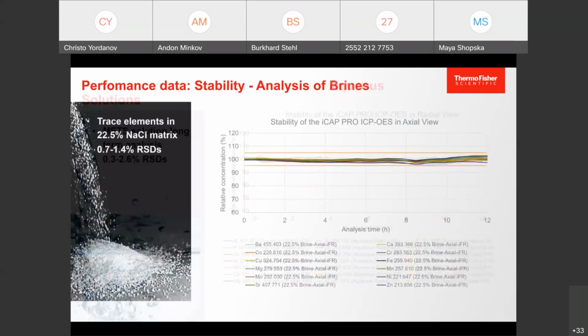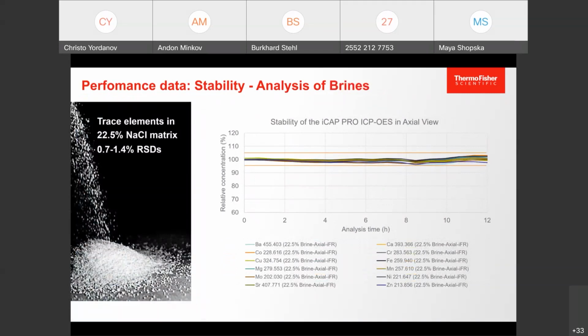And now we're coming to the real challenging stuff. It's 22% salt. You have to keep in mind, when more than 25% salt is in a water matrix, it turns from liquid to a solid. So when you've got more than 25% salt, it's in the middle between solid and liquid. You cannot really stir it, etc. And also here, with 25% salt, we have an average of, I don't know, 1 or 1.1% for a sample run over 12 hours. So really good stability.